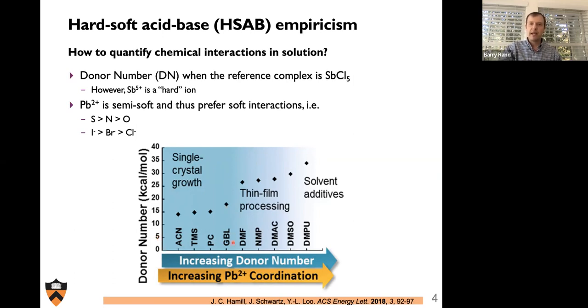And then those solvents that have an intermediate interaction with lead iodide, things like DMF and NMP, are preferable for thin film processing because they properly solvate the system and once cast can be removed from the film. And then things that would be considered as additives like DMSO or DMPU, these solvents should be used sparingly and often as additives because they coordinate very strongly with the solutes and can often be difficult to extract from the final processed film.